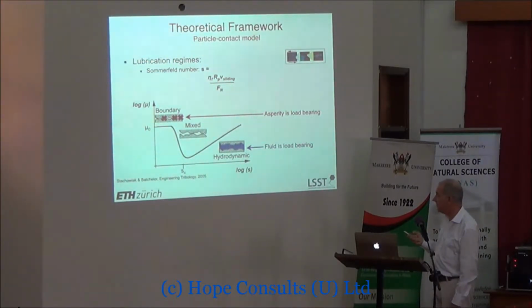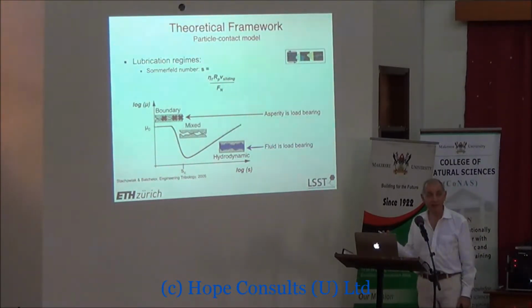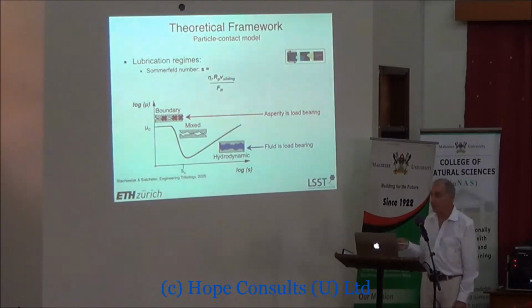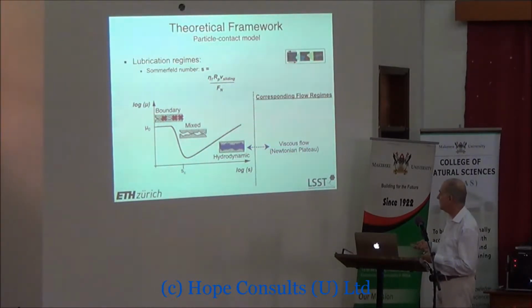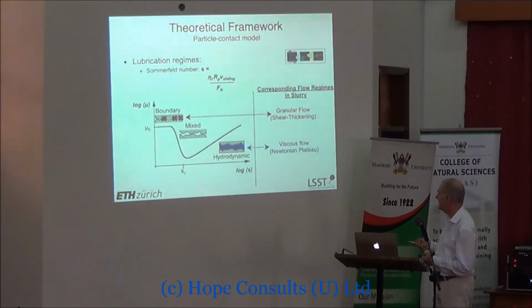So that's just the interface between these two regimes. But this is a very commonly seen behavior in bearings, for example, and very common for the lubrication engineer to use this. But it's never been used before to look at particles. When people think about particles, they think about particle collisions and momentum transfer. And so what we did is we tried to make a connection between these two areas and think of, this is the regime where we have the Newtonian plateau I showed you earlier. And this is when we start to go too fast and we bang the particles into each other and we push the particles into a boundary lubrication regime.